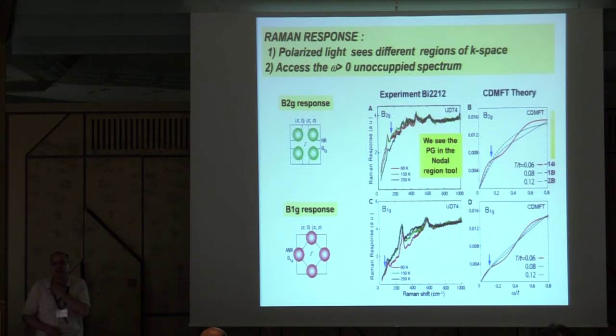And in the mercury compounds, which are cleaner, I think it is even more evident. So what we have done, we have calculated with linear response theory, starting from the Green's function we extracted with DMFT, the Raman response. And that is what we see also. Well, in the B1G, we have a loss of spectral weight. That is the signature of the pseudogap. And in the B2G, if I start from the same temperature, first I have an increase of spectral weight. That's normal in a metal. When you decrease temperature, the Raman response increases because the scattering time reduces. The slope is proportional to the scattering time. But at the lowest temperature, the red curve, there is a loss of spectral weight.